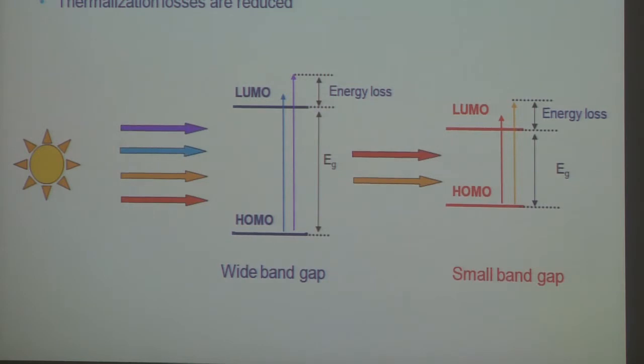So the tandem combination really gives you an enhanced effect. And if you look at the Shockley-Queisser limit for a tandem cell, it increases from 31% to something like 42%. And if you go to a triple, it goes to 48%. And if you go on and on, I think in the end you can get very close to the thermodynamic limit, actually.